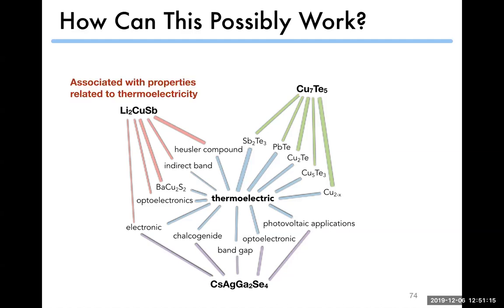There are a couple of ways that the model seems to be making suggestions. One is that a material may be mentioned with properties that are very closely associated with thermoelectricity. So in this case, it may be a Heusler compound with an indirect band gap. And those tokens that are being mentioned together might start pulling that material closer to thermoelectric. Another case is where a material may be mentioned in a study with other materials that are later discovered to be thermoelectric. So they were chemically similar in some way and studied together for that reason. And then later the materials may be discovered to be thermoelectrics. So this is a discovery that we've missed. We just haven't made it yet. It fell through the cracks.